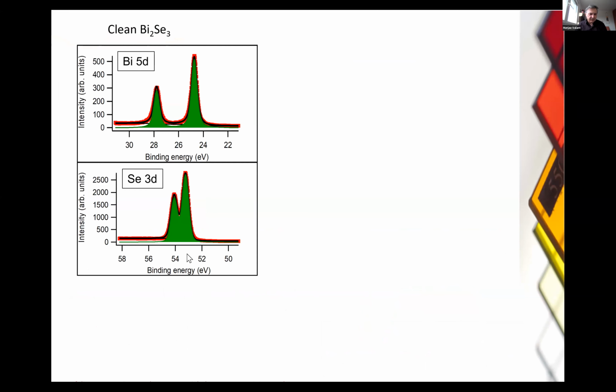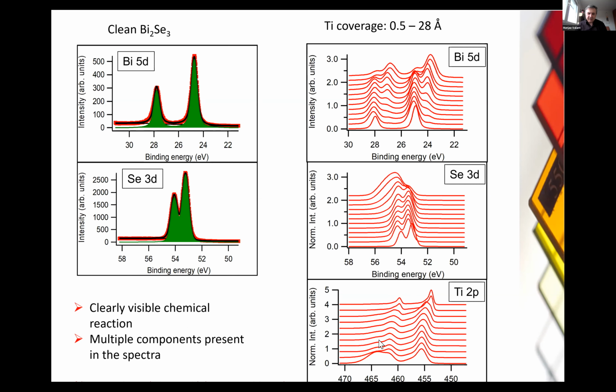So here is XPS of a clean surface of bismuth selenide. No surprises here. The peaks are at the expected binding energies for bismuth and selenium. Then we analyzed the system where titanium was deposited on top, at different nominal coverage, and here you have 3 plots for 3 different elements. You see we start with the clean one, and then we increase the nominal coverage. What you can obviously see here is that the shape of the spectra, of the peaks, is changing very much. This necessarily means that there is some chemical interaction going on.